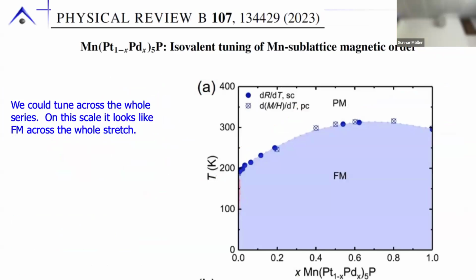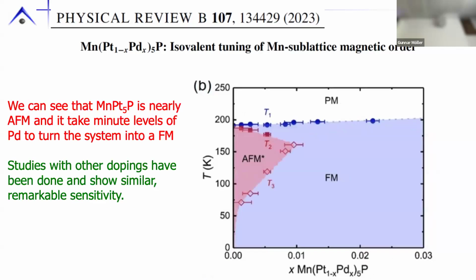Now, another example, we can have the manganese platinum palladium 5 phosphorus. It's isovalent and isostructural tuning of this manganese sublattice. And if you look at this scale, it looks like a boring ferromagnet the whole way. But if you look closely at the very, very small amounts of adding palladium, you see that the pure platinum is antiferromagnetic, and it takes homeopathic amounts of the palladium to get rid of this antiferromagnetism. And we actually have re-entrant ferromagnetism for some of these dopings. And we've been able to find that this host material, manganese platinum 5 phosphorus, you can find it in other types of dopings as well. So interesting for looking at the magnetic ordering of the manganese there.